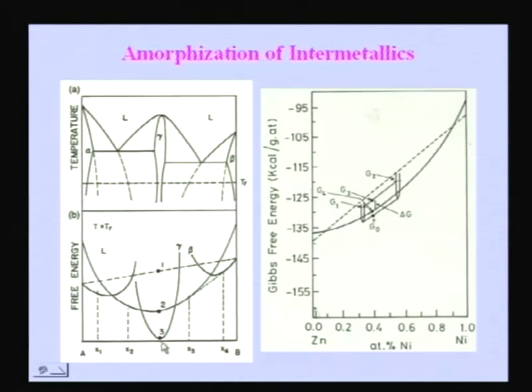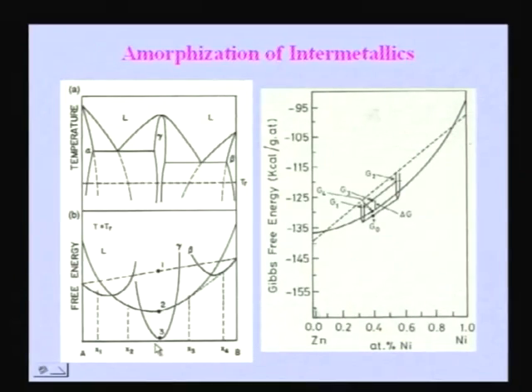But an intermetallic, if it has to become a liquid, it is not easy because there is no direct driving force. The liquid, or the amorphous phase, always has a higher free energy than the intermetallic. So what do we do?